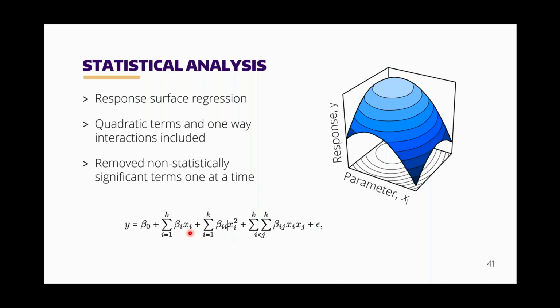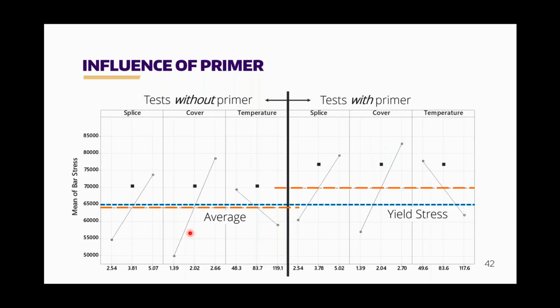And what the analysis allows you to do is slowly eliminate non-statistically significant terms. So the question is, are these terms good predictors for the response? And it turns out that not all of them are. And so you get some understanding of what's going on here. Right away at the beginning, Carolyn said that we did a scoping study to see what the influence of primer was. And so this is the results out of that scoping study. Because it was a fractional factorial design, you only get the main effects, which is the effects of the variables by themselves. And this was all done for a single bar size. So we didn't investigate bar size with this set of tests.